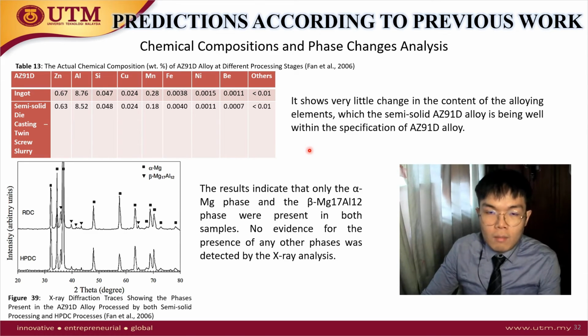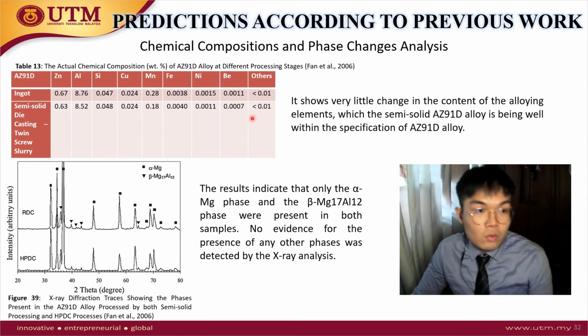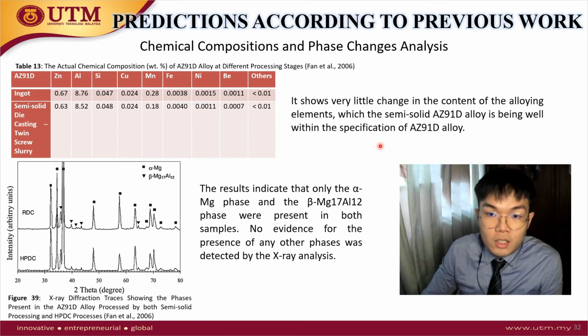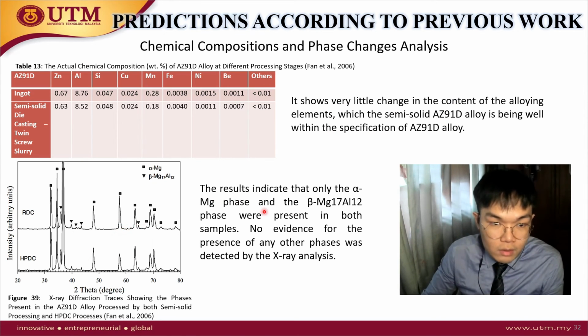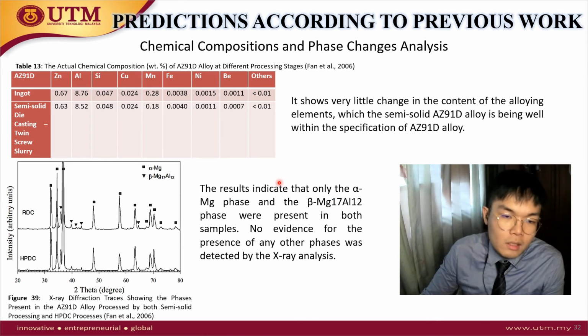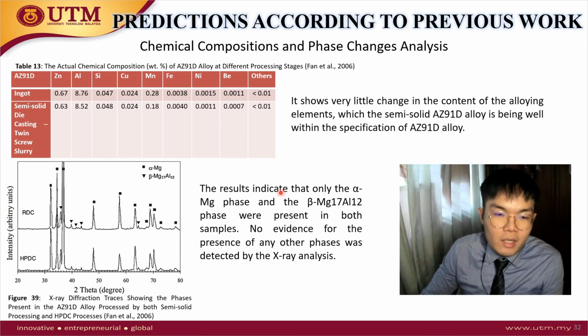This is to analyze the effect of cooling slope casting on the chemical compositions and the phase changes. So from the result, it shows very little change in the content of the alloying elements, which the semi-solid AZ91D alloy is well within the specification of AZ91D alloy. So it doesn't create a big change in the chemical compositions. So from the XRD result, the results indicate that only the alpha magnesium phase and the beta magnesium aluminum phase were present in both samples, and no evidence for the presence of any other phases was detected by the XRD analysis.